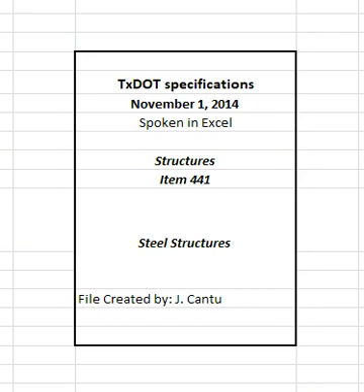Maintain the temperature uniformly throughout the furnace during heating and cooling so the range of temperatures at all points on the member is no more than 100 degrees Fahrenheit. 3.5.4 Machining. Machine the surfaces of expansion bearings so the travel direction of the tool is in the direction of expansion.